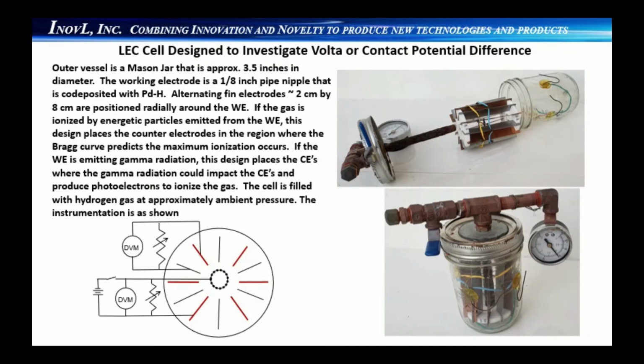This slide illustrates one of the cells we designed to investigate the Volta or contact potential difference effect. If the working electrode is emitting high energy particles, for example alphas, we know they will ionize gas, and based on the Bragg curves, 90% of those ions would be produced in the last 10% of their travel. For that reason, we designed this cell with an alternating set of fins of copper and zinc, positioned near where the ions would be produced.